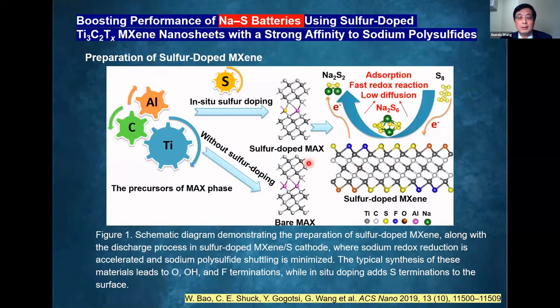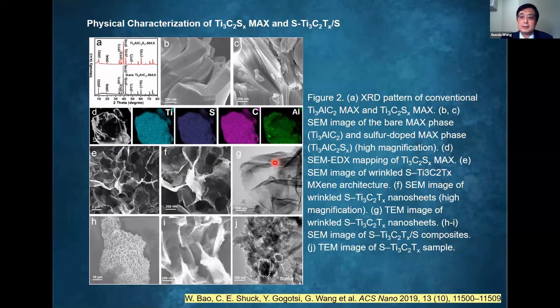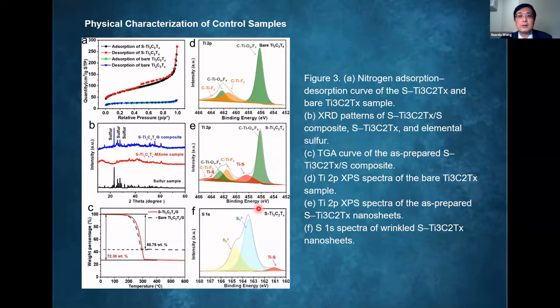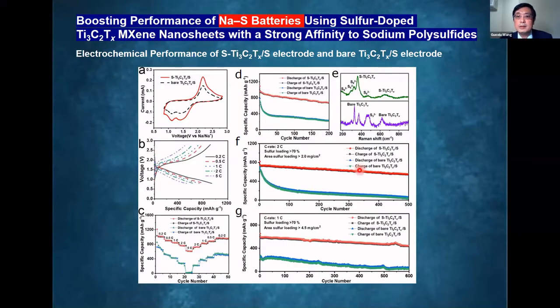And this is another work done by Weichai Bao and collaborators, with Dr. Shuck in Yuri's group. In this case, we prepared the sulfur-doped MAX phase in the first instance, and then we exfoliate the sulfur-doped MAX phase to sulfur-doped MXene. And then we utilize this sulfur-doped MXene as the cathode host material for sodium sulfur batteries. So this XPS characterization can clearly show sulfur has been successfully doped inside the MXene phase. And this is the electrochemical performance. You can see the sulfur-doped MXene cathode shows better electrochemical performance than the non-sulfur-doped MXene cathodes.